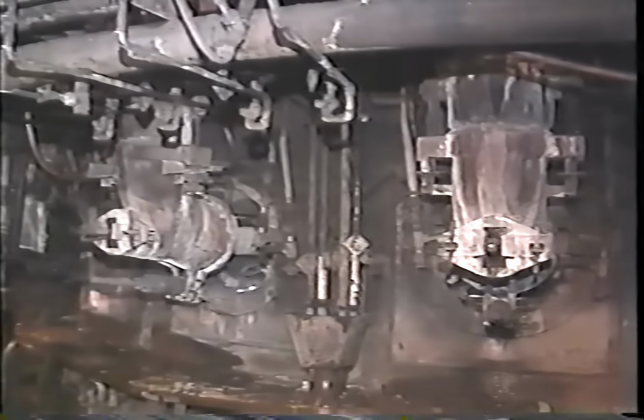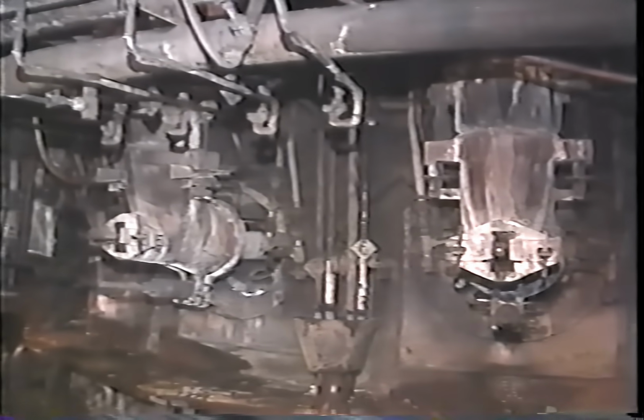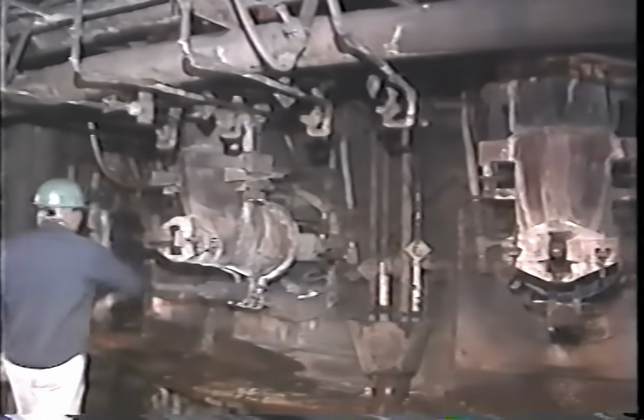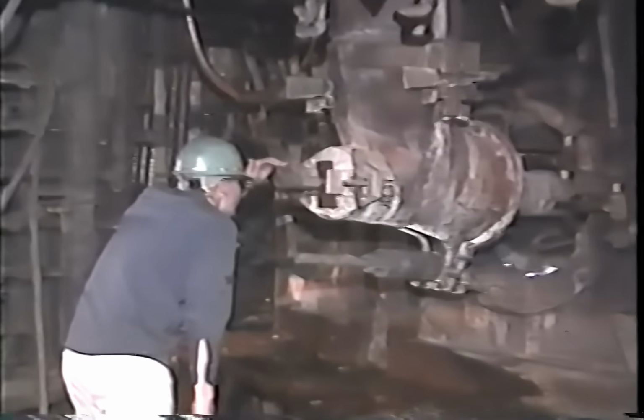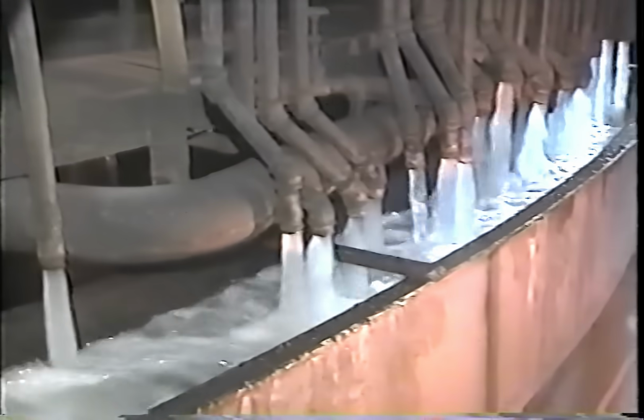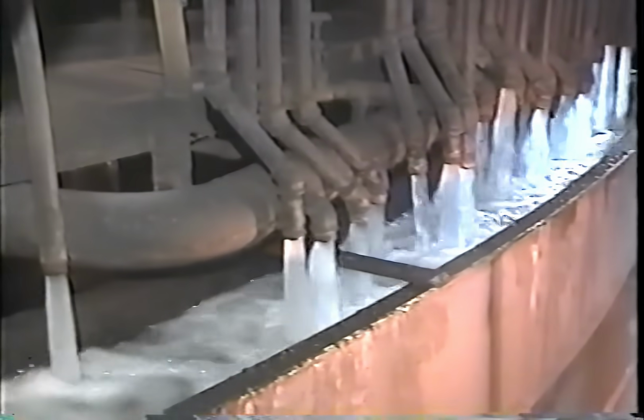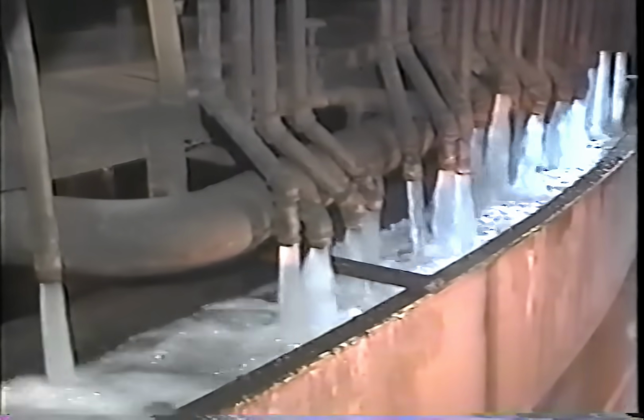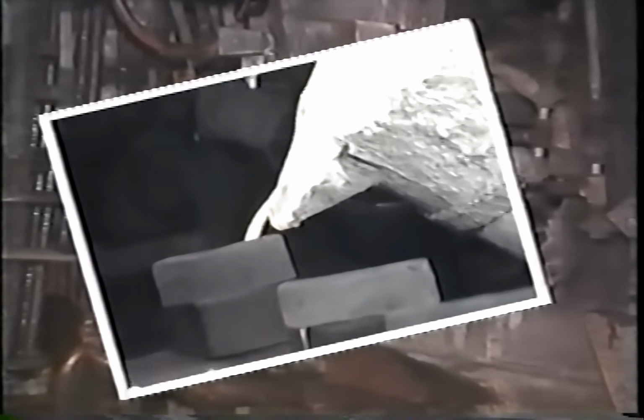A hot blast line carries the heated air from the stove to the bustle pipe, which surrounds the furnace near its base. 18 tuyeres, branching off the bustle pipe, inject the hot blast into the furnace. A view through the peep sight shows the combustion taking place inside at nearly 4,000 degrees Fahrenheit. Water sprays cool the furnace jacket to keep the furnace structure from distorting in the intense heat. The tuyeres and other internal coolers were made at Bethlehem Structural's brass foundry of high-purity copper for maximum heat removal efficiency.